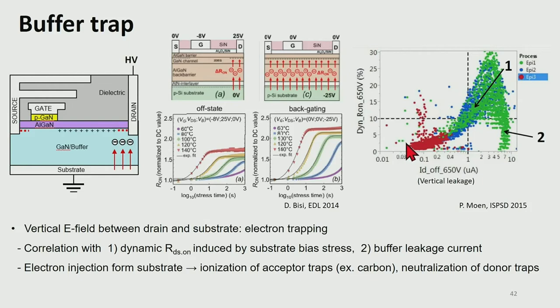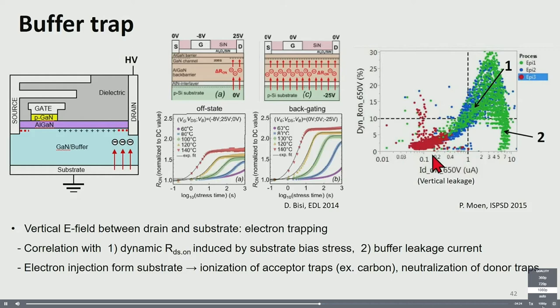Also, similar to the surface trapping mechanism, we can reduce the electron supply to the GaN epi. By improving the aluminum nitride nucleation layer and also the buffer layer, we can suppress the electron injection into the gallium nitride epi. As one example, this right figure shows that there is a good correlation between the vertical leakage current in the off state and the dynamic RDS,on. So basically, by making the buffer more insulating, we can improve the dynamic RDS,on performance by suppressing this buffer trapping mechanism.